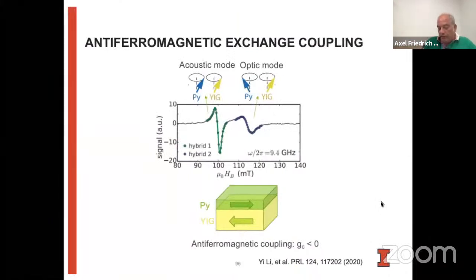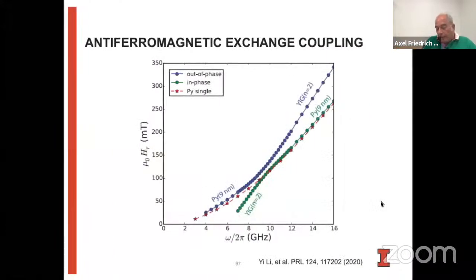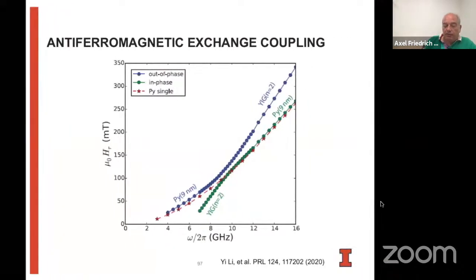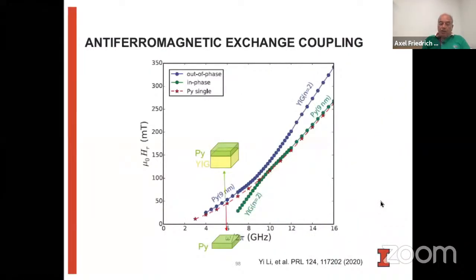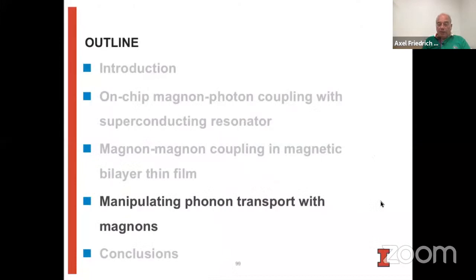And so the coupling constant is negative here. You can see this because the mode of the permalloy on its own, without any yttrium iron garnet, lies slightly below the permalloy mode that's on top of the YIG. That's just because of the negative exchange coupling that you get when the permalloy is on top of the YIG.